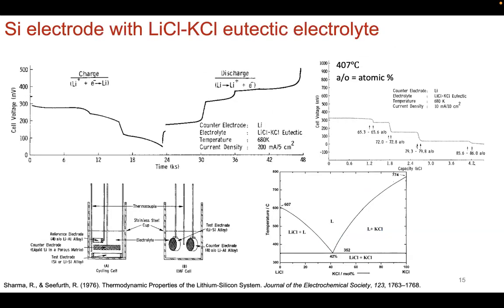So one of the first studies that were done in the 70s, in 1976, by this group, looked at just that lithiation and delithiation. And in a eutectic, so at 407 C, and why 407 C? That's because that's the molten state. So that's the eutectic point right there. So at this particular composition of lithium chloride to potassium chloride, at 407 C or 680 Kelvin, you're in the molten state. And you can see at elevated temperature, the discharge profile or the lithiation profile of silicon in this eutectic electrolyte is exactly what you're expecting.